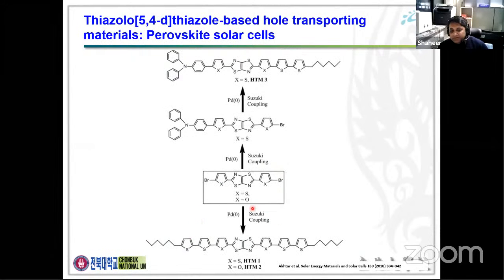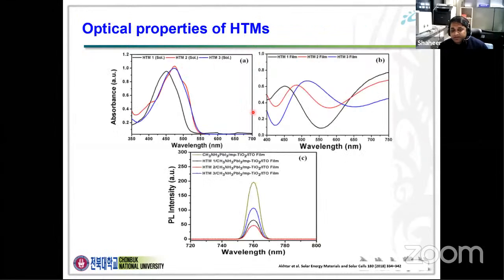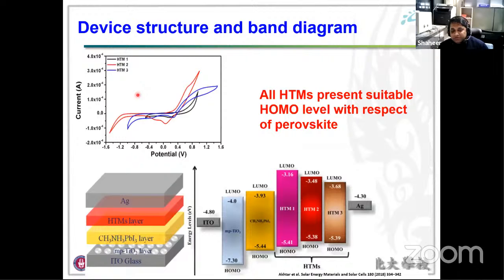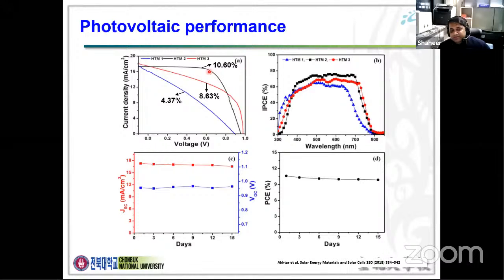So in our laboratory, we synthesized thiazole type HTM materials, and we found they show very good electrical properties. The optical property covers the whole visible region, and it also shows good quenching with the perovskite and TiO2, and good alignment with the perovskite HOMO level. When we check the performance, it is around 10.6% in the case of HTM2, which has 2 thiophene with 1 furan.